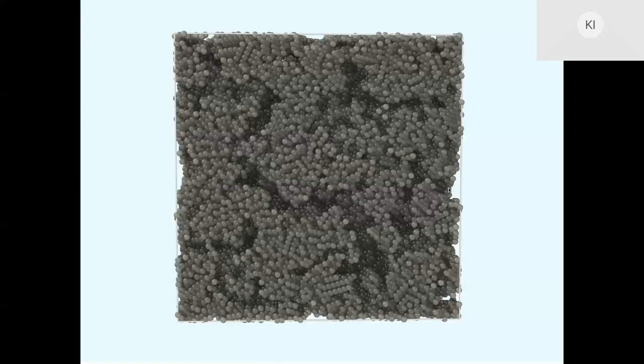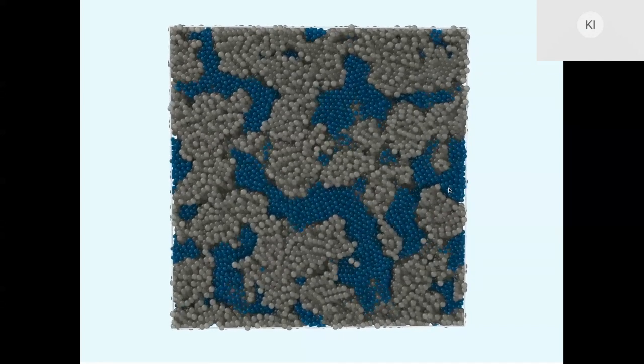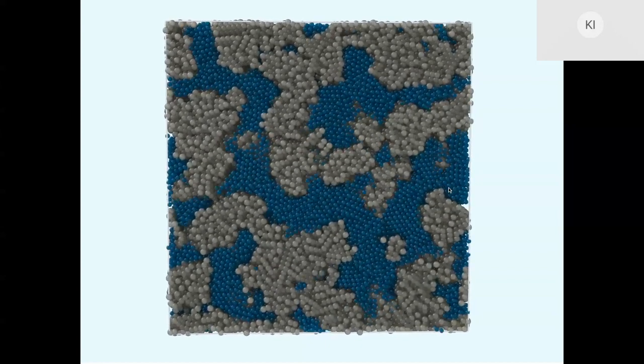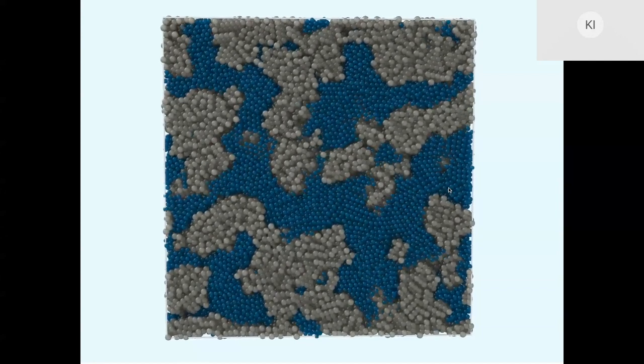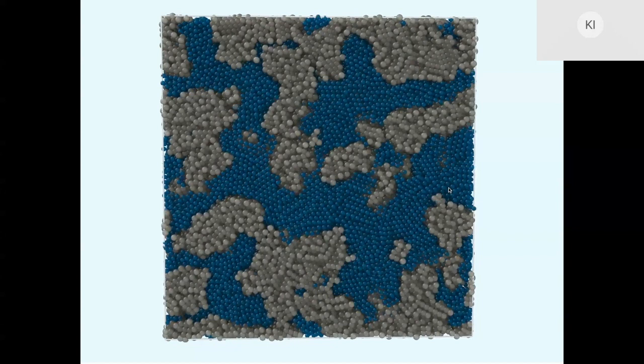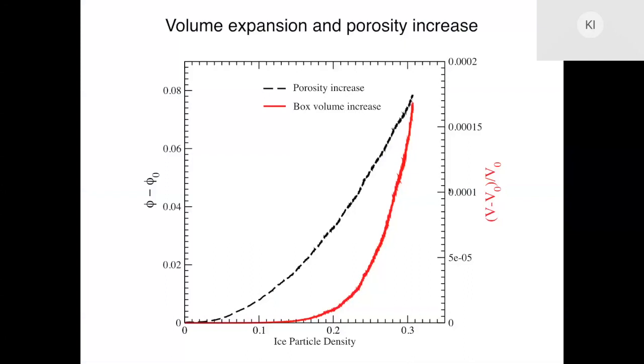So we start with the cement configuration, and we are introducing the grains of ice with a grand canonical Monte Carlo simulation, and we are observing that first the ice is clustering in the pores of cement and eventually is percolating the structure. Let's go and see a bit in detail what is happening there. Here I'm plotting how the porosity is changing and also how the box volume increases with the ice particle density. So we see that first the porosity is increasing inside the system, so that means that ice is helping CSH to pack better, but after a while the whole system starts to expand.